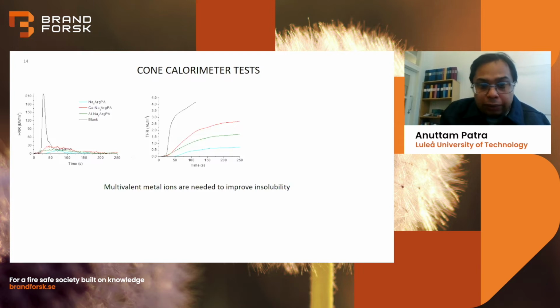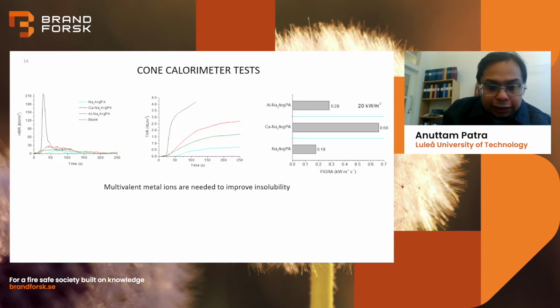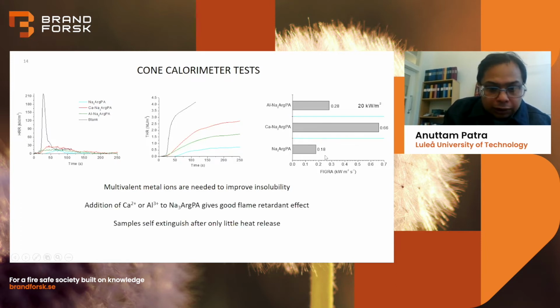We used multivalent metal ions because their water solubility is much less, like calcium and aluminium. And you can see they are still quite good, especially aluminium. The FIGRA index is very comparable with the sodium salt. And in this case also, the samples can self-extinguish if it caught fire, or most of the cases there was no fire observed when they were exposed to flame.